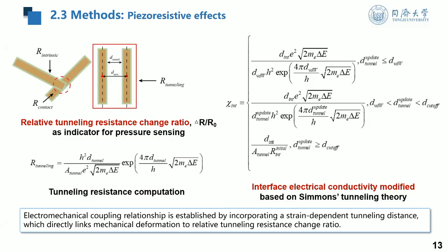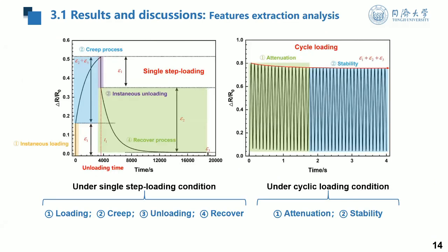This is for the piezoresistive effects. Here we mainly consider the strain-dependent tunneling resistance change. This is our feature extraction analysis. Our model can well capture the four stages for the step loading conditions. First, the instantaneous loading and the creep process, and then unloading and finally recovery.